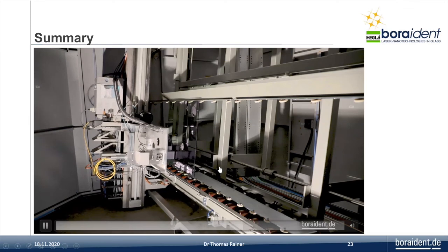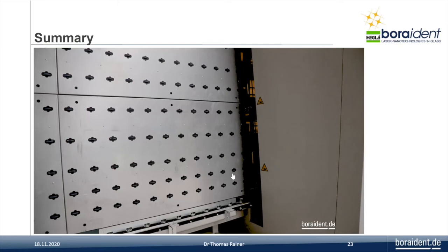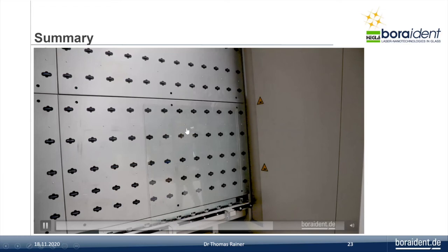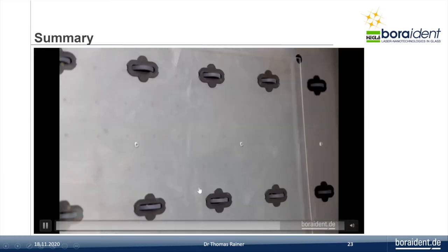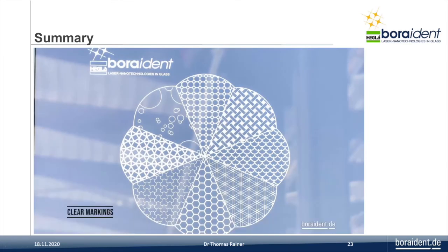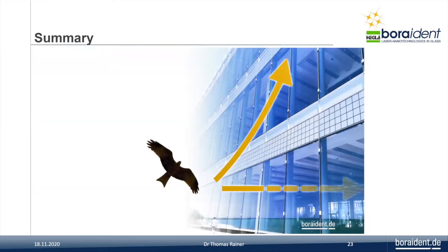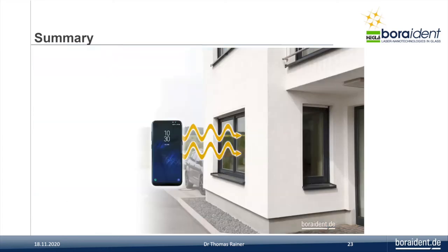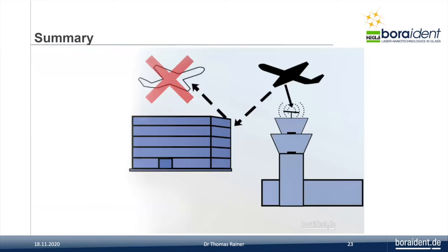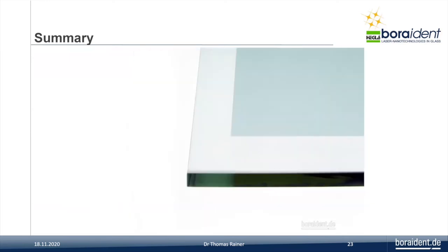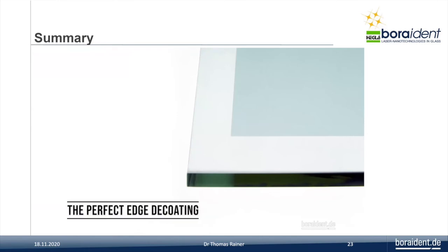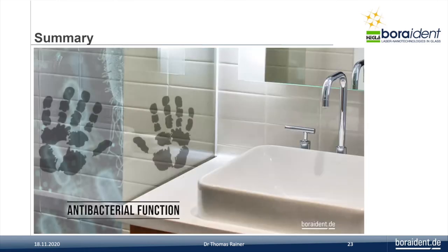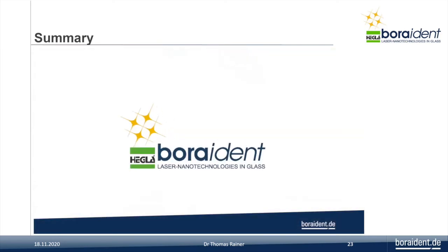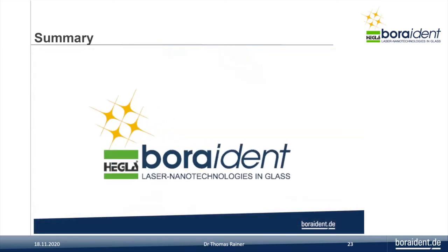In this case, we structure a bird-friendly structure in the pyrolytic coating of a glass pane. And it's very hard to see. If we go a little bit closer, we see the points that prevent birds from hitting the glass surface. So we can make clear markings, bird-friendly glass, cell phone-friendly glass, and we can avoid collisions in the air. And at the final end, if we bring material to the glass surface itself, we can make antibacterial functions inside the glass surface itself. This is all I have to say about laser functionalization of glass.